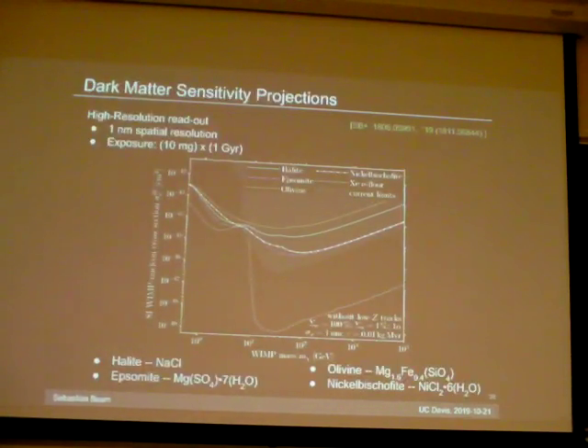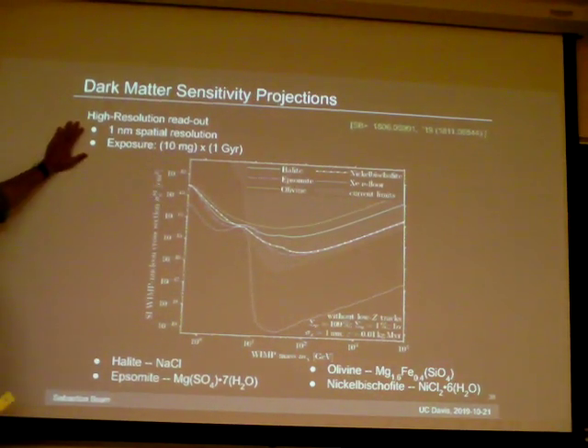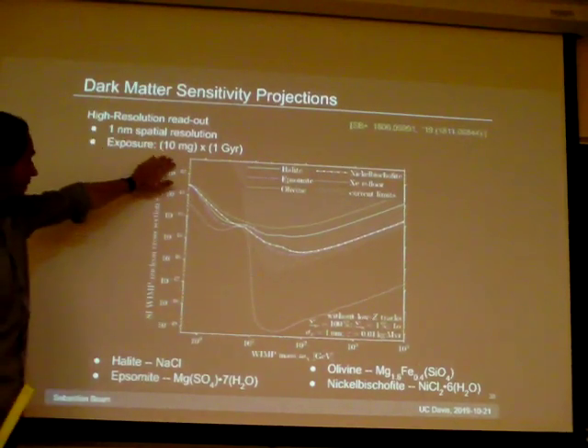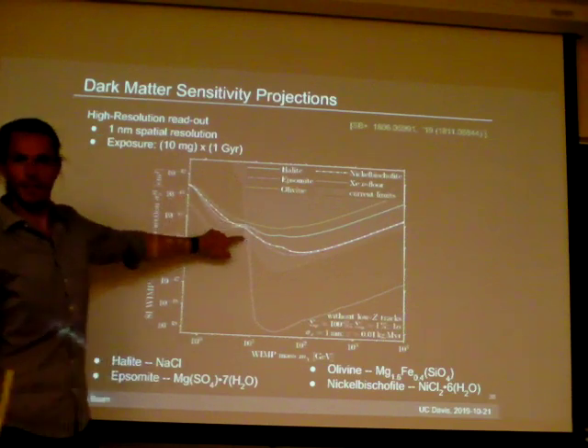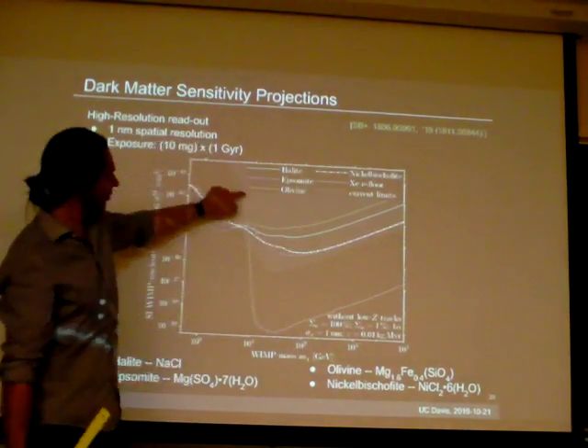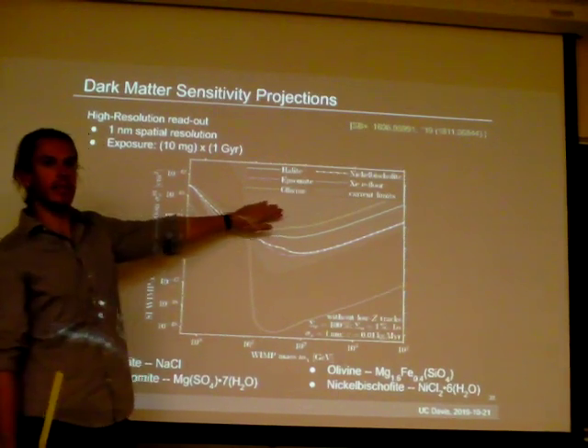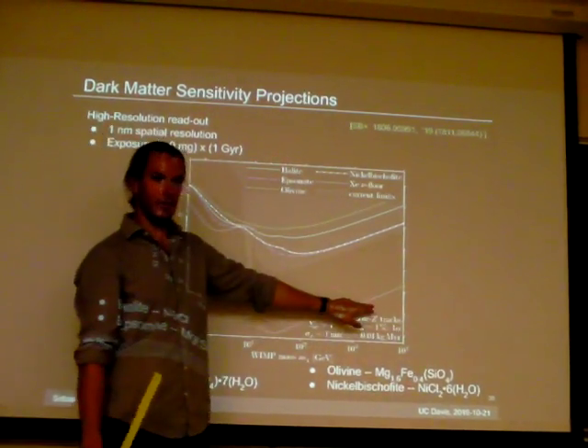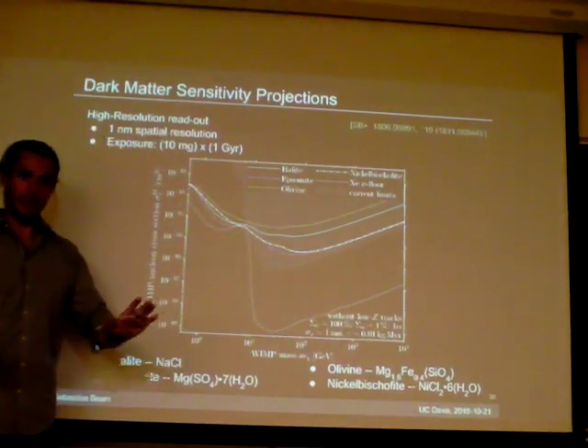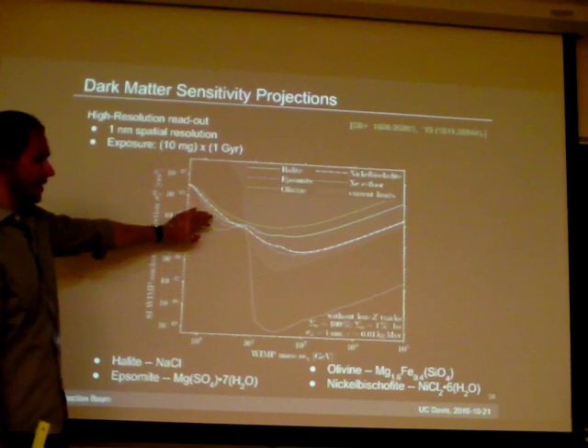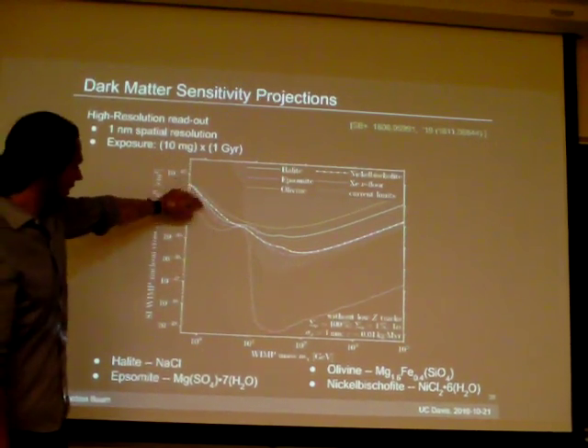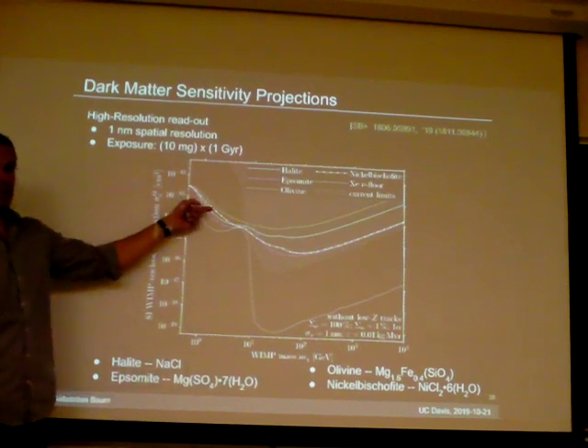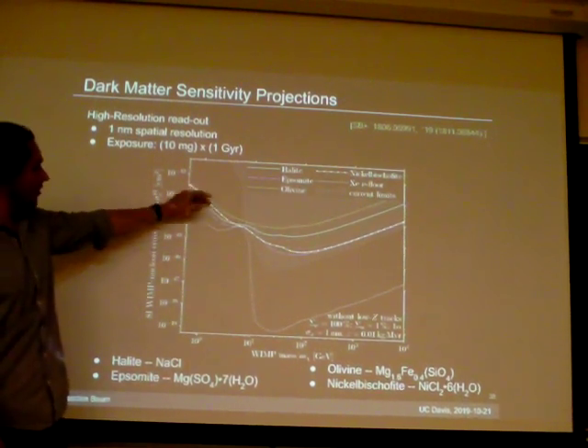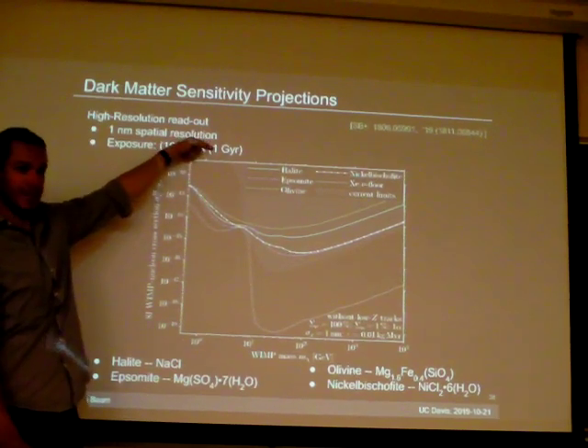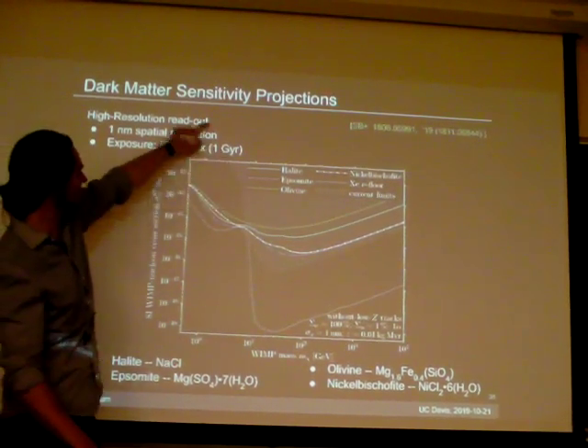So this is what the reach looks like when we calculate it. This is the high resolution helium ion beam readout idea, 1 nanometer resolution and an exposure of 10 milligrams times a billion years. Here in gray, it's probably very hard to see on this slide, but this gray curve and shaded area are current limits from direct detection experiments. Here, just to orient you, is the xenon neutrino floor. Now the neutrino floor looks different for each target and each experiment you run, so this is just for orientation, what it would look like in a normal xenon experiment. And all these colored lines are different target minerals that we calculated. So you see the reach is orders of magnitude better than anything one can do today, right? The experiments today sit somewhere up here.